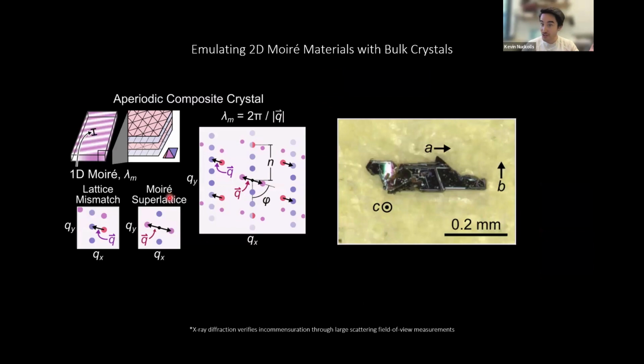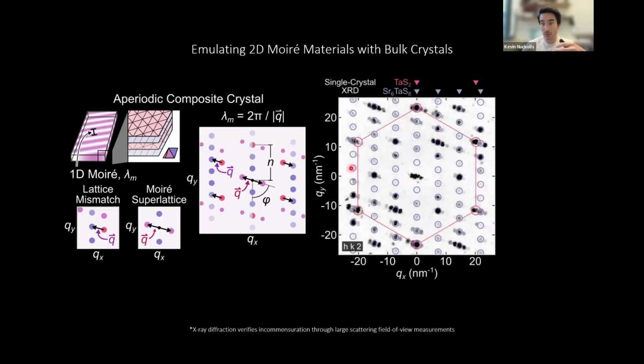So with these diffraction signatures in mind, we'll do single crystal X-ray diffraction to understand the symmetries of these lattices. When we perform these measurements, we see a very dense, complicated spectrum of diffraction peaks that are hard to make sense of at first, but we recognize that we can use a lot of symmetries of this diffraction pattern in order to pull out the different sublattices.